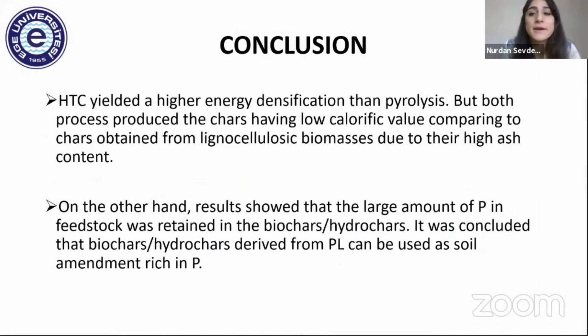In conclusion, hydrothermal carbonization yielded a higher energy densification than pyrolysis, but both processes produced chars having a low calorific value compared to the biomasses due to their high ash content. On the other hand, results show that a large amount of phosphorus from the feedstock was retained in the biochars and hydrochars. So it was concluded that the biochars and hydrochars derived from poultry litter can be used as soil amendment rich in phosphorus.